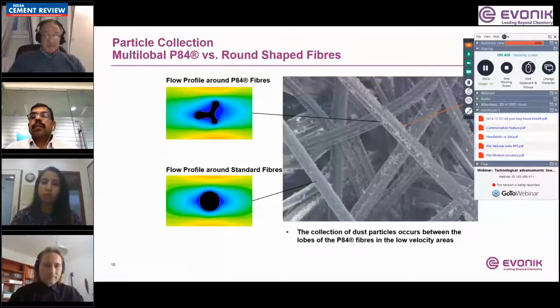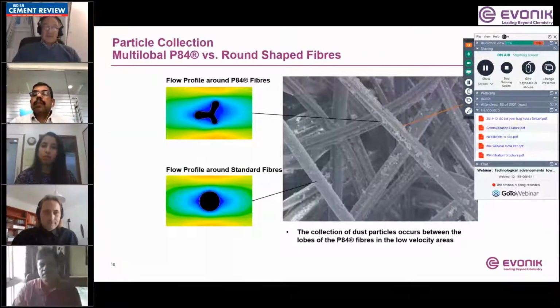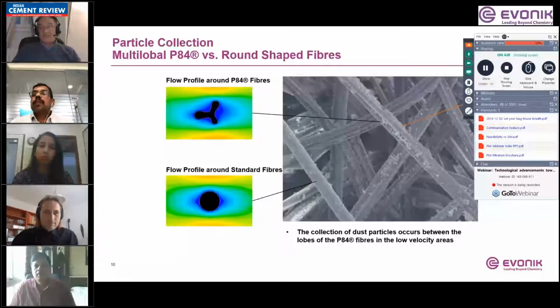Furthermore, the specific surface offered by P84 fibers, if you consider the weird shape of P84 fibers, even their circumference is increased compared to any other fiber of same dtex. So we have an increased specific surface of 65% if we talk about standard fibers, and that's a tremendous advantage when we talk about filtration. This translates into a very important advantage for you when evaluating bag-house expansions to cope with increased production capacity in case. And this happens quite often nowadays.